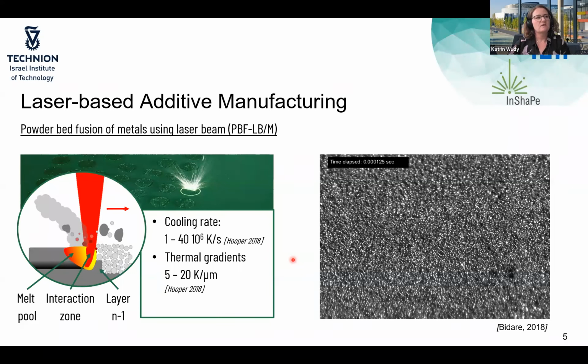And it's not only black bodies; every surface, especially metals, at this temperature starts emitting this light. The only difference from a black body is that we now also have the emissivity. If we remember that the emissivity for a black body is 1, all other surfaces on Earth have an emissivity lower than 1. That means they need more temperature to start shining in the visible region. But in the temperatures that we expect to have in the project, in the melting pool, they're above 2000, so we can measure them with spectral cameras. Can you go on, please?